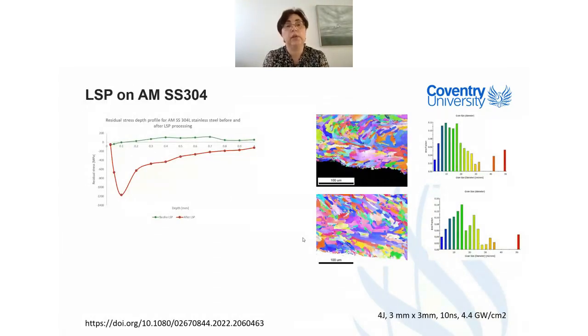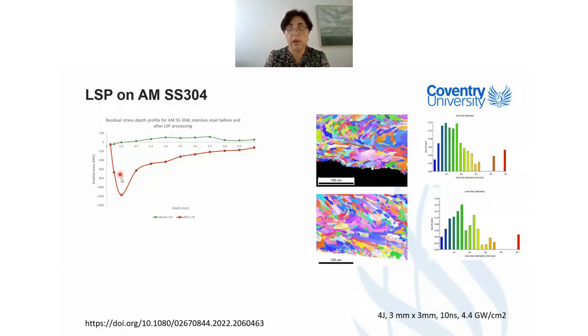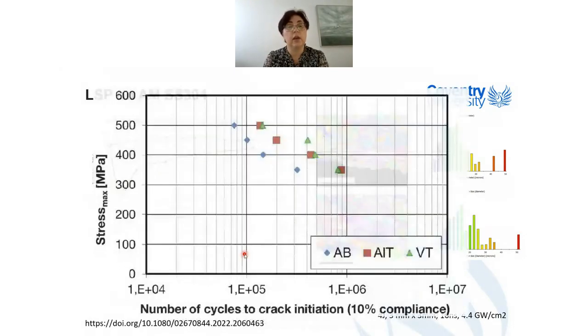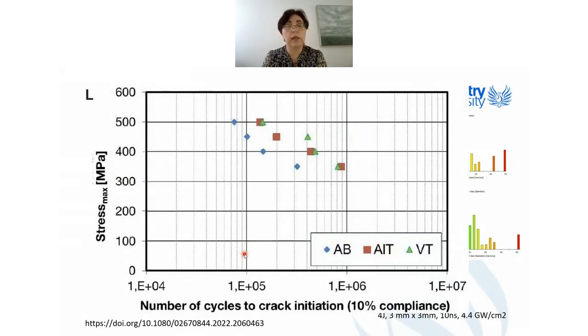After the tooling, one of the sectors we were looking at is additive manufacturing, and all of us are aware how interesting this technology is to industry. But at the same time, there are several problems like voids, pores, tensile residual stress, and surface roughness. So we were investigating if we can, for example, eliminate tensile residual stress. Can we increase part performance by mitigating near-surface porosities and allow those parts to be used in more sensitive applications? We were also trying to improve the roughness,